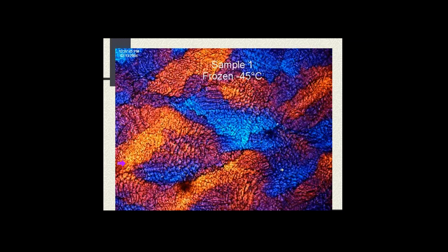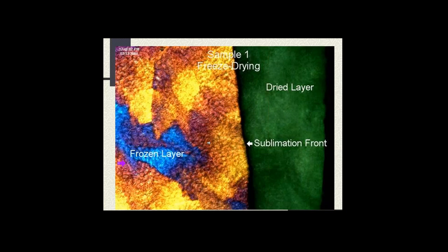So basically we take the sample, put it on the microscope, freeze it down to about negative 45 and collect an image. We want to show an image of the frozen layer. Then we kick on the vacuum and we start drying at a safe temperature. So the DSC says, you got a glass transition. I think in this case it was around negative 37, 38. So we're probably drying this about negative 40 because we want to dry and get an intact dried layer. So this is the frozen layer. This is the dried layer, which is intact. And Ruben will talk about more.